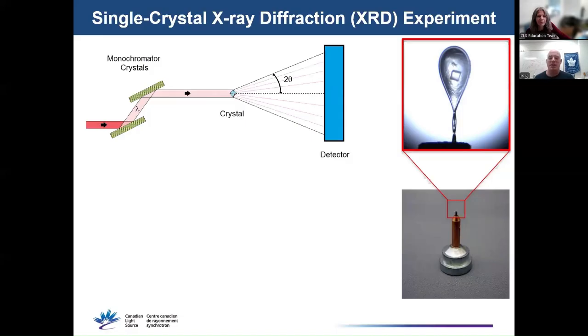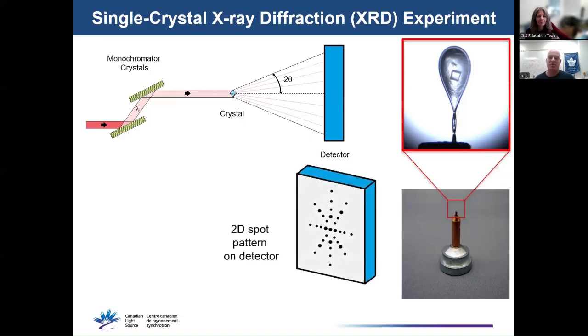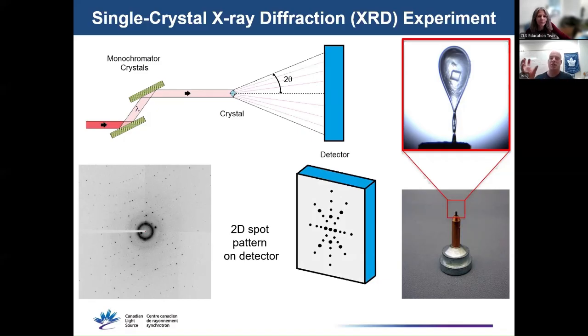When we focus X-rays on the crystal, we get a pattern of spots on our detector. This is a cartoon pattern, but an actual pattern looks something like this. The pattern depends on the orientation of the crystal. So we collect patterns of spots at many different crystal orientations by rotating the crystal in small steps and collecting a new pattern at each step. Typically, we collect hundreds of 2D patterns from a single crystal. Computers are then used to analyze the 2D patterns and to determine how the atoms are arranged in the crystal.